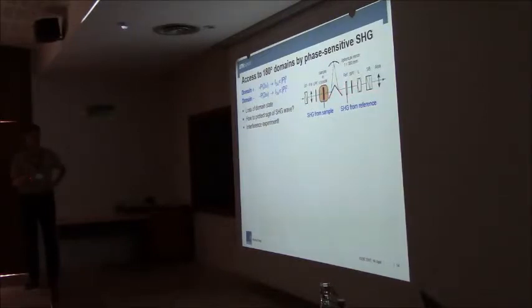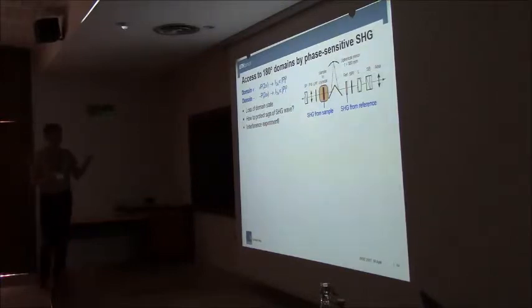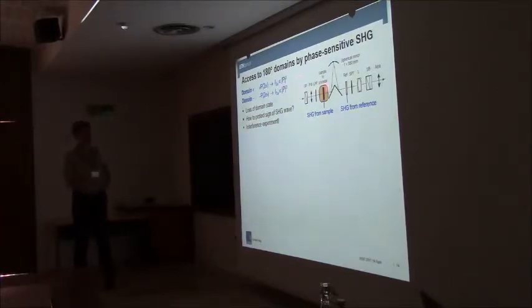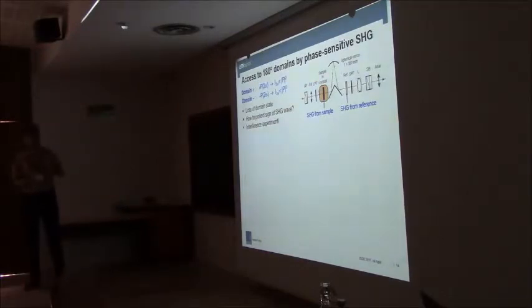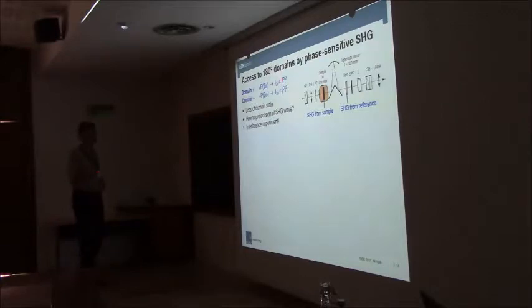And then you overlap the two, and you have a fixed frequency wave from your reference crystal, and you have the domain-dependent signal from your sample. So you would get reference SHG plus P of 2 omega, or reference SHG minus P of 2 omega, squared. So by an interference experiment, you can translate this into more or less intensity. And then you have saved the phase of your light wave, which would otherwise be lost. And you can distinguish domains.